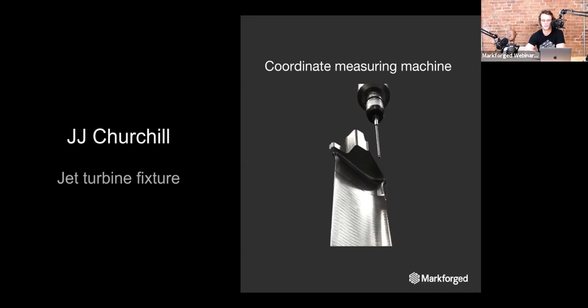And so you can see the end effector of the CMM in this picture on the slide. Basically the machine knows the precise location of its end effector, and therefore it can make really accurate measurements of the part as it touches multiple points on its surface. So during this process, it's critical that the turbine not move or deflect. This is typically achieved through a custom aluminum CMM fixture that the part is clamped into. But as you may guess, based on the theme of this presentation so far, custom machining the fixtures is expensive and time consuming. It costs them about $2,000 per fixture and had a lead time of about 2 weeks.